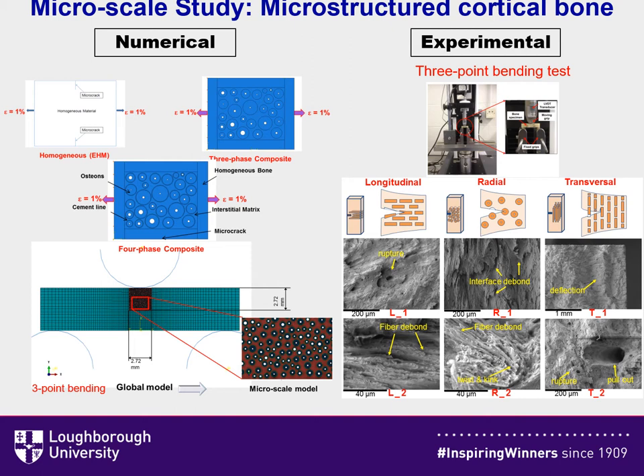Three different formulations for the model were used. One was of the effective homogeneous media. Another was for the three-phase composite, which accounted for the osteons, interstitial matrix, and the Haversian canals, which are effectively, in mechanical terms, the empty voids in this case. The four-phase composite material also included direct introduction of the so-called cement line. This is a layer with a thickness of 2 to 5 microns, which surrounds the osteon material.